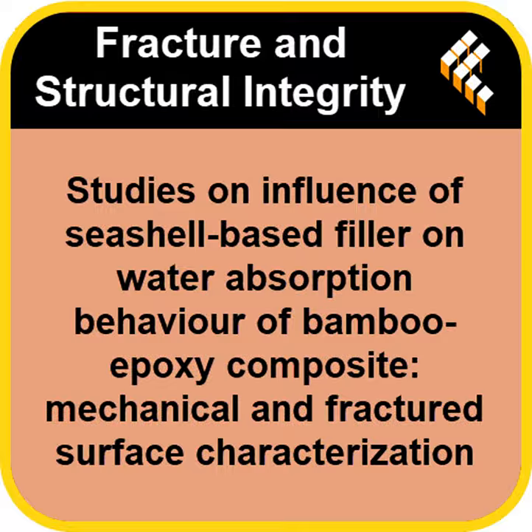Now, compare that to the optimal 6% filler composite. What did that look like? Much, much cleaner fracture surface. Far fewer signs of fiber pullout, less obvious matrix degradation. Crucially, you could actually see the little clamshell particles embedded uniformly within the epoxy. So they weren't just floating around, they were properly integrated. Exactly. They seemed well dispersed and bonded within the matrix.